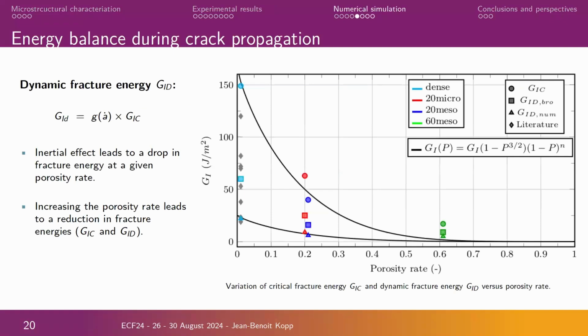So by doing that, it is possible to estimate the fracture energy as a function of the porosity rate. And we have some values obtained by numerical simulation, but by considering experimental data. So as you can observe, we have a decrease of the fracture energy as a function of the porosity rate. But of course, the value depends strongly on how you estimate the fracture energy, how you consider the dynamic effects. So by our approach, we have the value just over there, and we found some very low fracture energy.